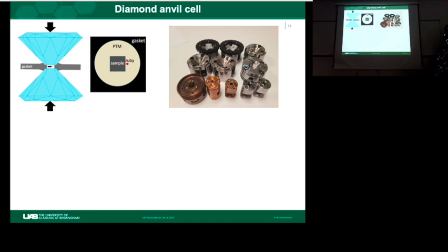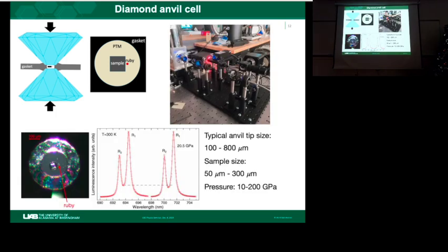Either in a high magnetic field environment, so we use these cells made of copper beryllium. And if we do single crystal X-ray diffraction, we use this other type of cell with a large aperture to access the higher 2 theta angles. And this is called a panoramic cell. We can allow the signal to be measured in the fluorescence geometry. We can take inelastic X-ray data.